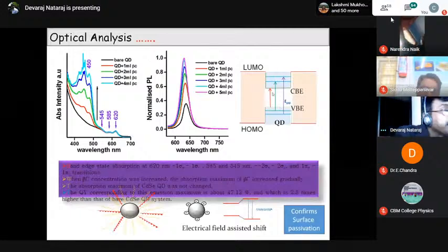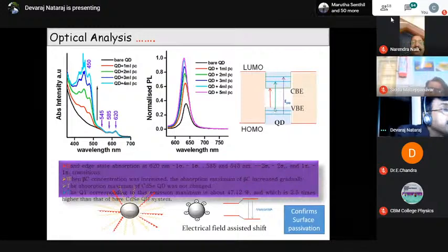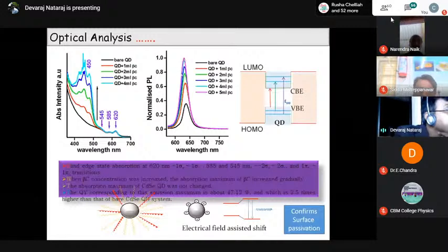If I increase the energy of the excitation, the electrons are shifted a little bit farther in energy position. Thus, by slowly increasing the excitation energy, we are able to increase the electron energy level position slowly to a higher energy value. As long as the electrons are within the band offset, the electrons recombine with the holes and emit very strong emission. And because of the type 1 band confinement, the electron probability of finding outside of this box was very low, and therefore there was a shift in the emission band position towards the blue side.